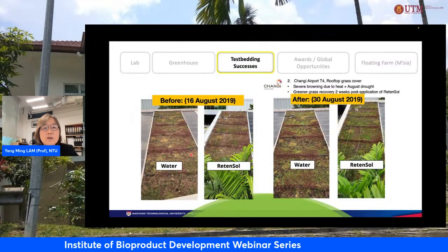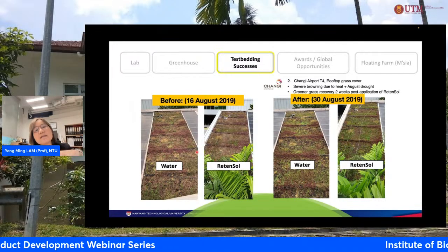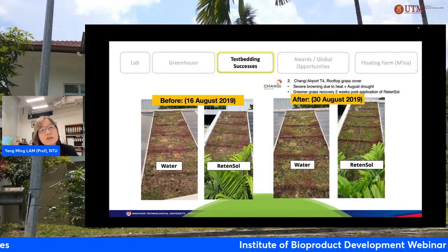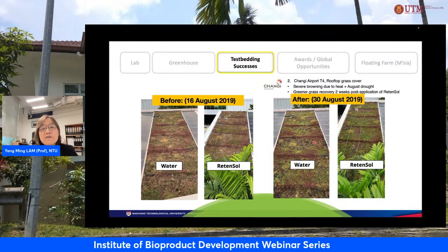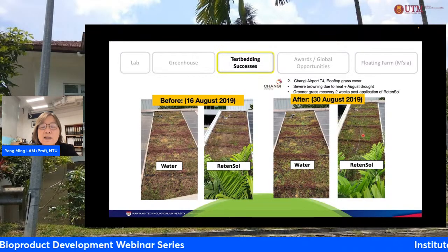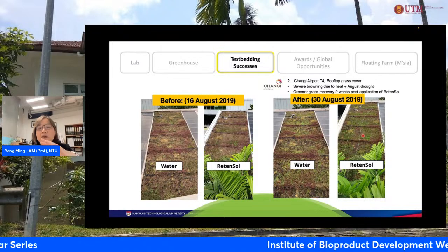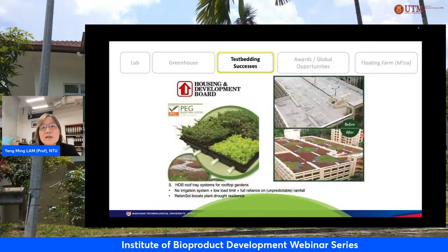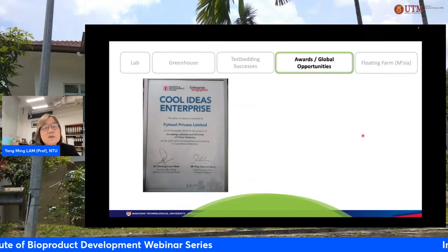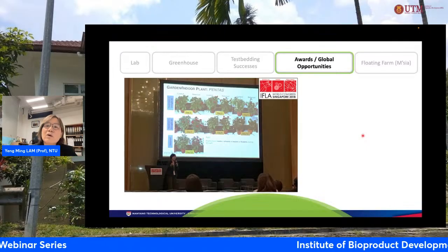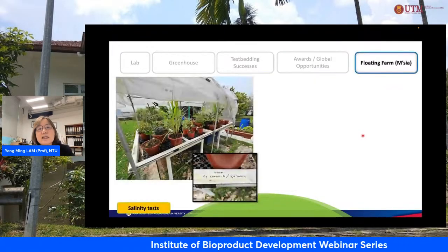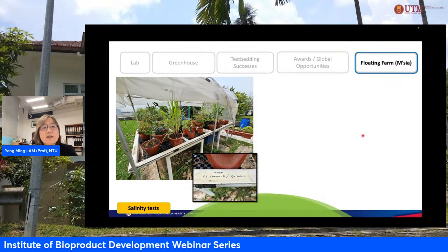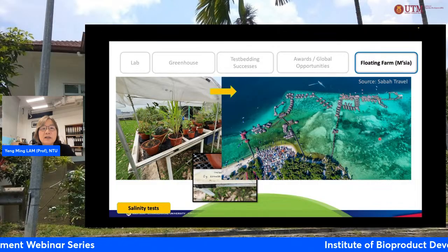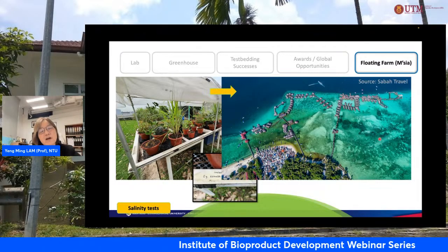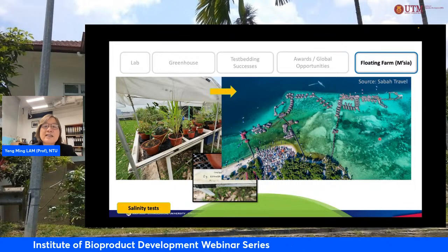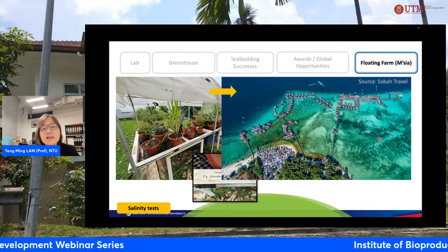So we have also tried it on Changi Airport. On top of Changi Airport, some of the walkways, they have rooftop, which is actually green. In the past, with only water, they were not able to grow green plants. But with RetenSol, after 2 applications, you can see that actually the RetenSol helped to maintain the rooftop to be more green. So water now can actually be held by a shallower amount of soil. So we also work with the Housing Development Board, and then also with some of these international platform where we shared our results. And the last one was actually we tested off one of the floating farm in Malaysia. And what we did was actually together with a urban farmer, we float the urban farm out into the sea with this testing of this RetenSol. It also helped to extend the life of these vegetables and plants in these floating farms.